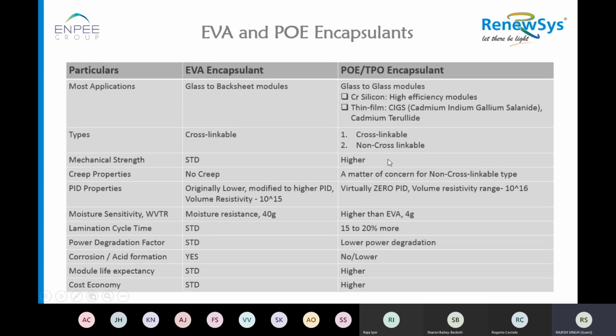Mechanical strength of POE is more. POE also has a property called creeping if it is not properly cross-linked, because, as I said, there are two types of POE available in the market. So non-cross-linkable POE can give creep, especially for glass-to-glass configuration of modules. PID is one property which is very good for POE encapsulant because they are naturally electrically insulating in nature, and its volume resistivity is 10 to the power 16, unlike EVA which is 10 to the power 15 or lower. POE is also better in moisture properties, in terms of moisture barrier and sensitivity to moisture.